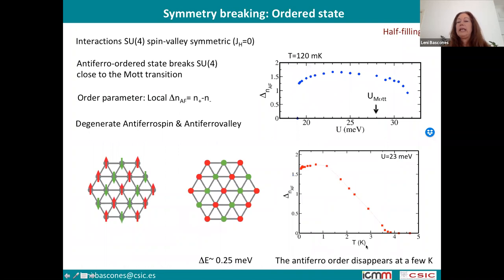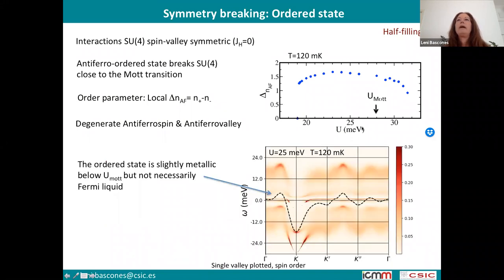The state remains up to a temperature of the order of 3 Kelvin, which is compatible with the energies that we observe, the difference in energy associated to this state. And interestingly, if we are close to the Mott transition, but still below the Mott transition, we find that this antiferromagnetic state is metallic. So most of the time, normally, antiferromagnetic states, not always, are insulating. But if we are in this region, this is metallic, but this is not necessarily Fermi liquid. We find some regions in which it's non-Fermi liquid.